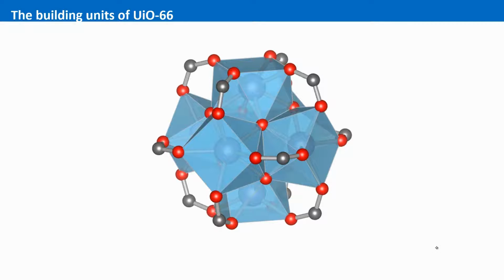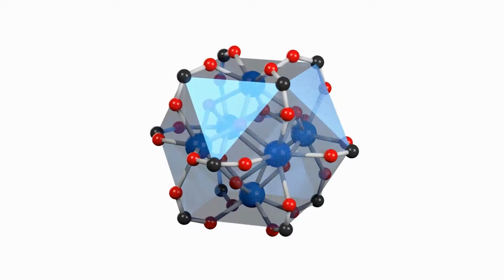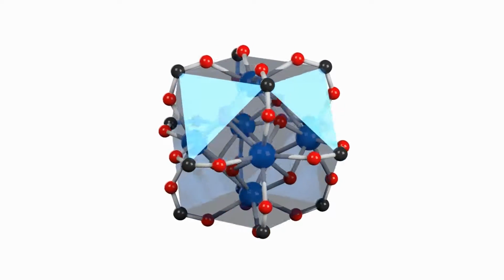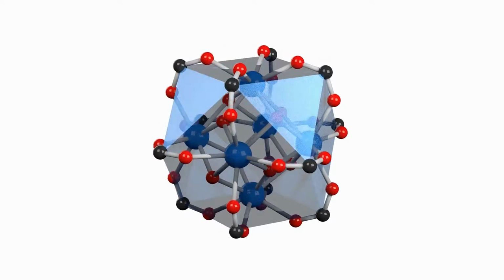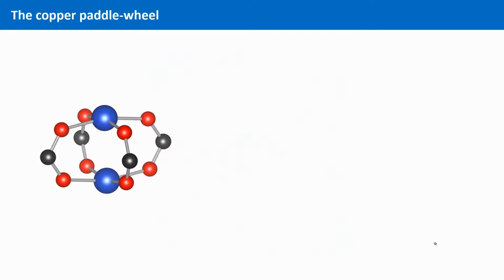Again, a cluster is formed from metal and oxygen ions. If we want to describe the inorganic building unit again as a geometric shape, then this would be a cuboctahedron. The points of extension of the inorganic SBU are again the carboxylic carbons. Not every metal forms these large clusters with carboxylic acids. When copper 2+ is combined with the same dicarboxylic acid again, a different cluster is formed.